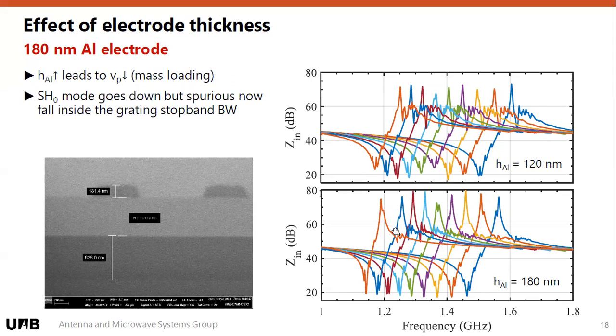So you can see here in the measurement that we have a low amount of energy, or low coupling, to the spurious mode above FP. And clearly, if you compare two similar resonators from the top plot and the bottom plot, we have a better QP and they are slightly wider in terms of coupling. Here's just a cross SEM, a FIB cut that Chevy did just to make sure of the thickness: you have 180 nanometers of metal, then 140 nanometers of lithium niobate, and then 600 nanometers of silicon oxide. So this is our LNOI structure.